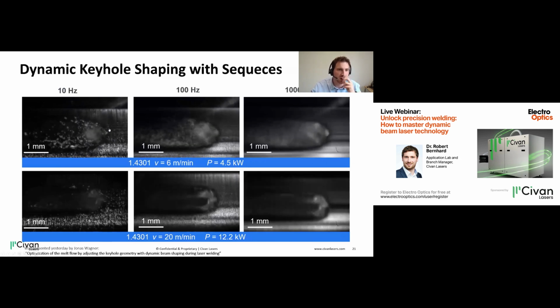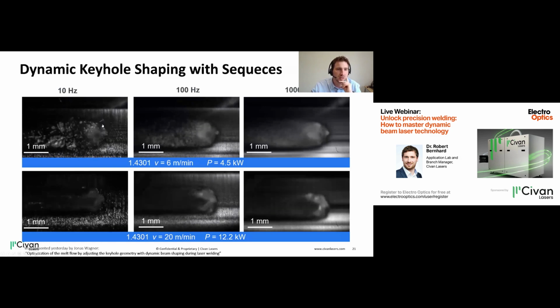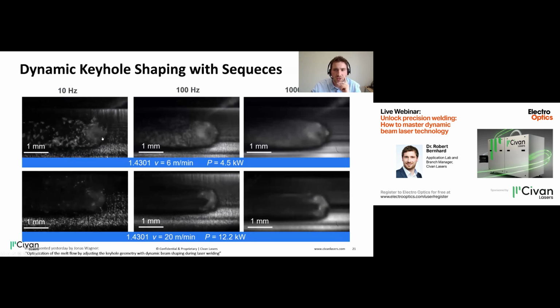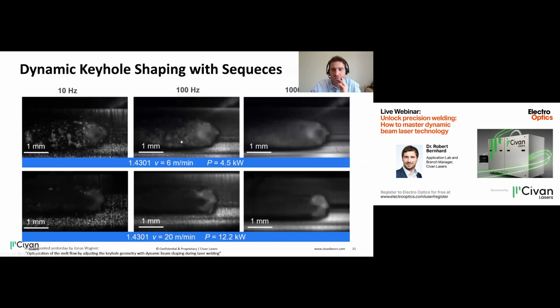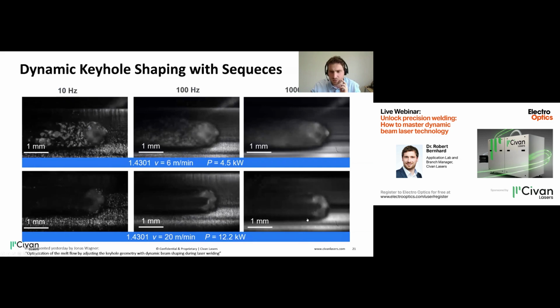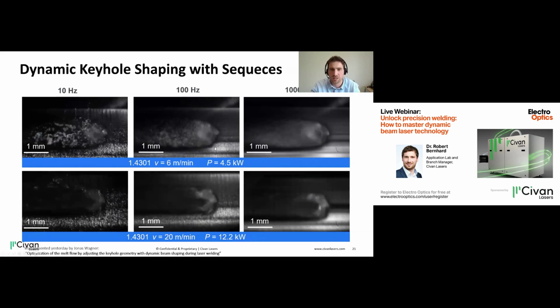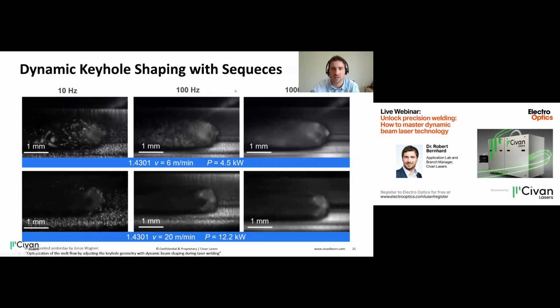So as you can see, one beam shape on the left side really leads to a lot of spatter and material flying outside of the beam. But if we increase in speed, the melt pool really becomes calmer and in turn results in better welding results.